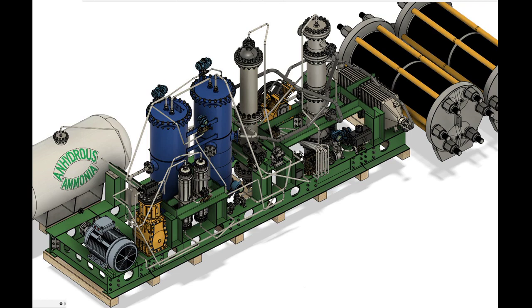In addition, the corrosion behavior of various commercially available stainless steels and nickel-based alloys as possible construction materials for the components which are in direct contact with the selected ionic liquids is evaluated. The results show a very high corrosion resistance and high stability for all of the alloys tested in any of the 5 selected ionic liquids.